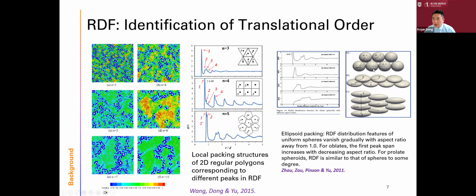And also for spherical particles, we can see the distribution also has a split second peak, but sometimes because of non-symmetric shape, we will have different peaks in the RDF. So this is one of the structure descriptors showing the different packing structures of different particles.